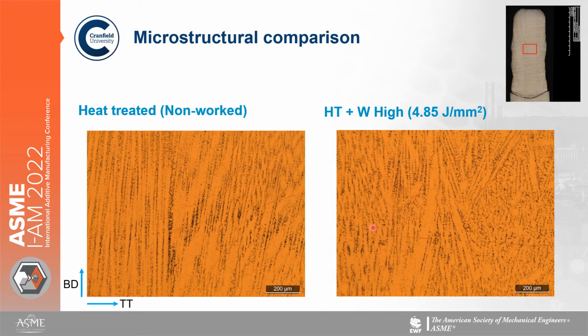And if we look at the middle of the sample, you can see some remelt lines. So there's a remelt line here, and then in the worked material, there's a remelt line here. And again, you can see the disruption in the texture of the microstructure.